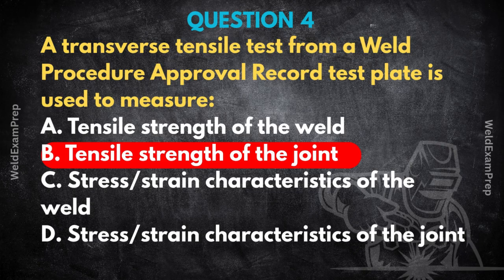Whichever fails first. Precisely. It verifies that the combined structure, as produced by that specific welding procedure, meets the minimum required strength for the application. It's a fundamental check on the procedure's capability to make a sound, strong connection overall. So if you just wanted to know the strength of the weld metal itself, you'd use a different test, typically an all-weld metal tensile test, where the specimen is machined entirely from the deposited weld metal, usually taken along the length of the weld, not across it, or sometimes a longitudinal tensile test. But the transverse test is about the joint. Okay, that's a really important distinction to grasp then.